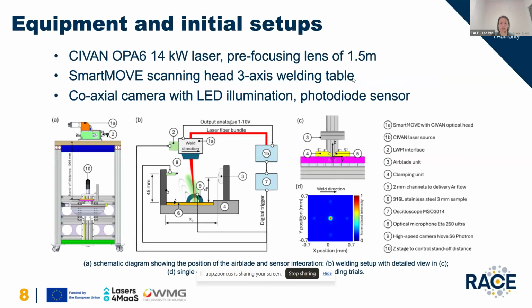So this is the system set up at WMG we've used for our welding trials. We are using a CIVAN 14 kilowatt laser to deliver the beam through a CIVAN optical scanner. And also we have an XY table paired with the system which allows our plates together with a jigging to move in the XY direction, and the Z direction can adjust the focus position. This is slightly different from other systems we used traditionally, because it didn't come with shielding and air blades combined, or let's say integrated into it.